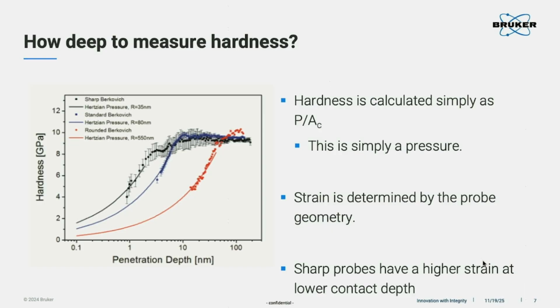So this is the indentation data measured on the standard sample we call fused quartz. If we look at this, the quartz hardness is around 9 gigapascal, right? So before the plastic deformation, you cannot get the hardness value. This is the reason why you see the data going almost from the bottom to the stabilized zone.